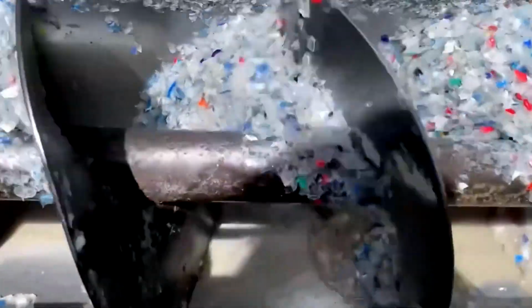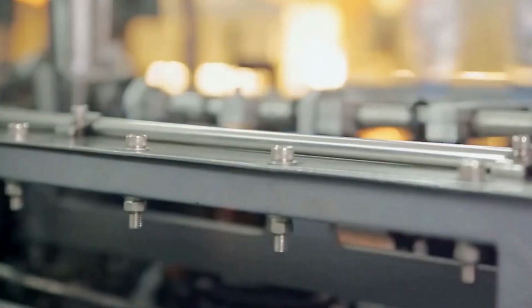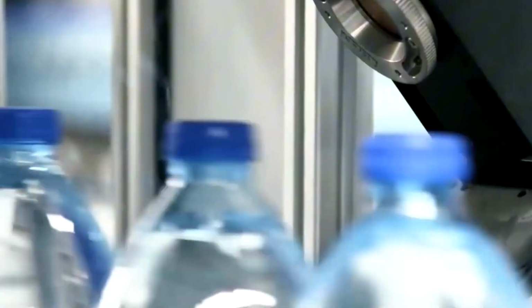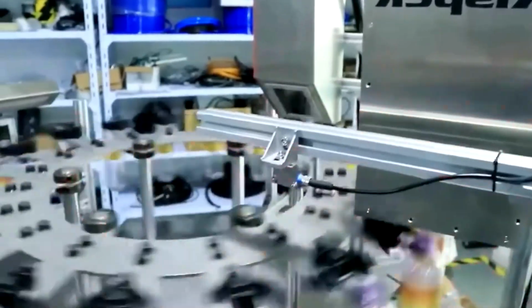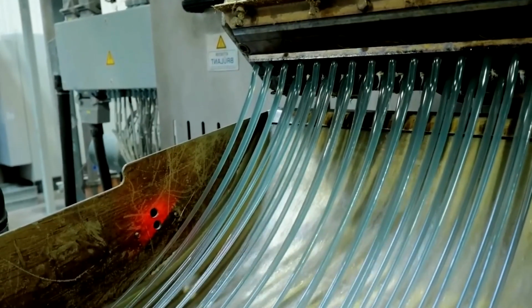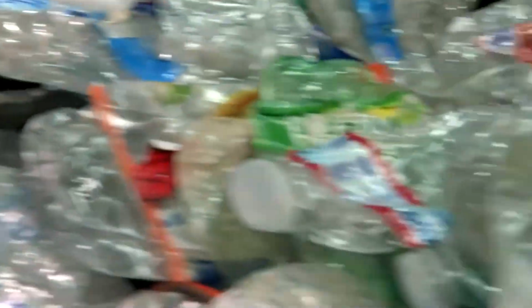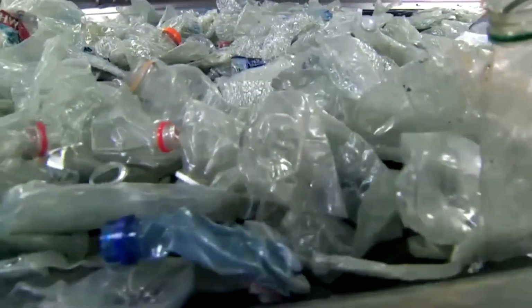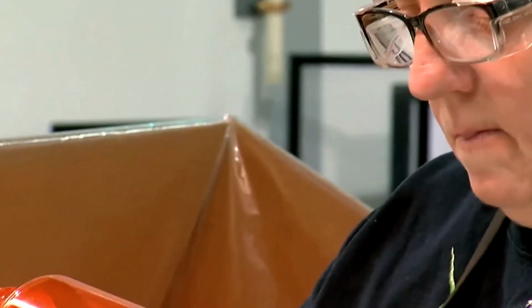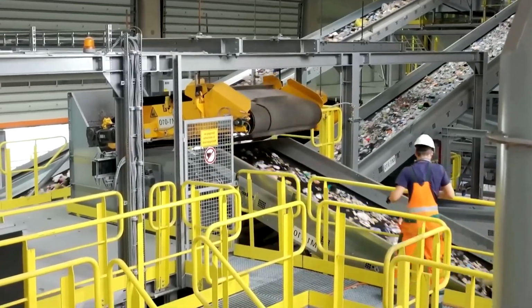One can notice how the bulky containers disappear into the unit, emerging seconds later as fragments only a few inches in size. This grinding step not only reduces the material's bulk, but also enhances energy efficiency in later stages. Because the plastic is broken down into fragments, it melts more quickly inside the extrusion unit, cutting electricity use by up to 40% compared with melting solid plastic chunks. The granulation phase also acts as the first level of size control, ensuring the feedstock is consistent.